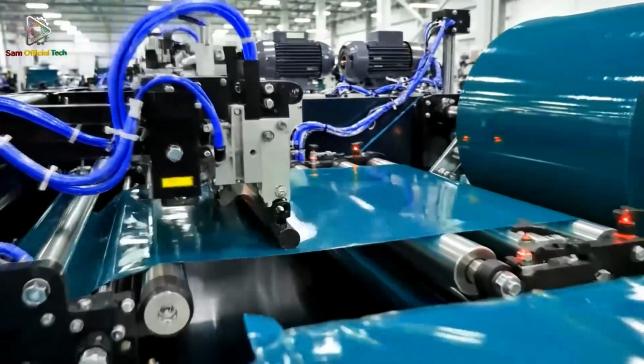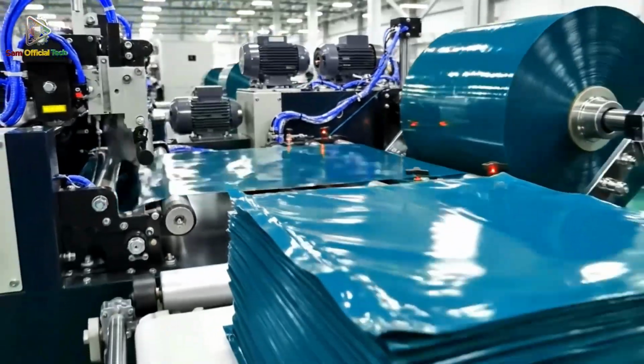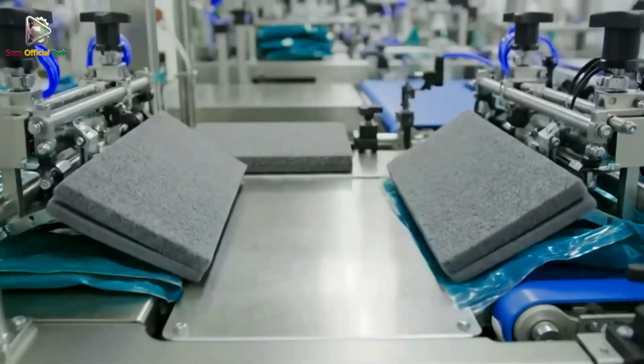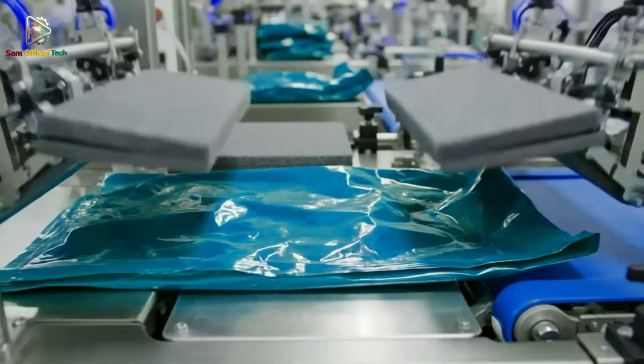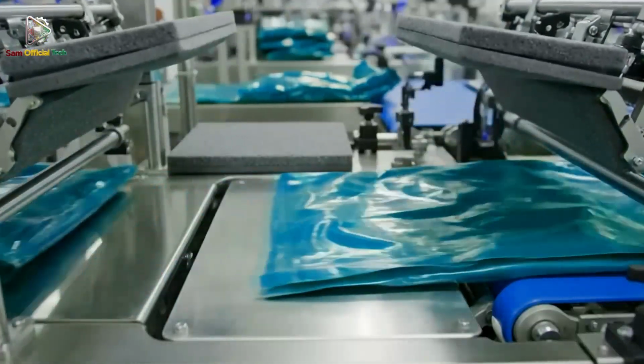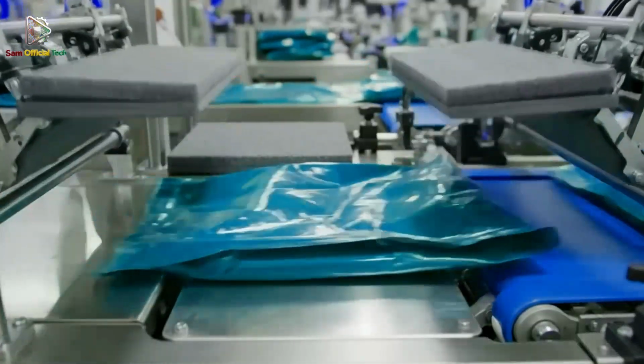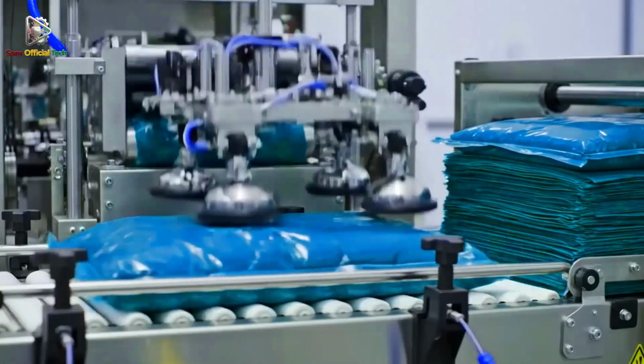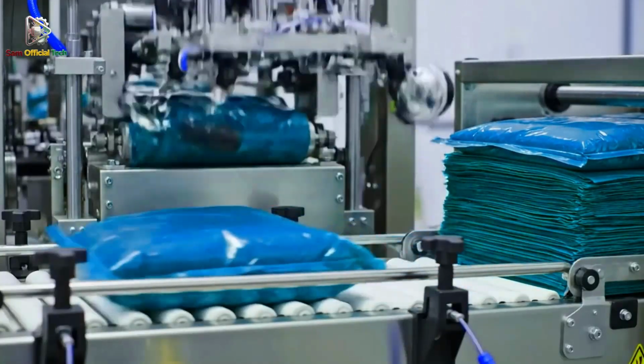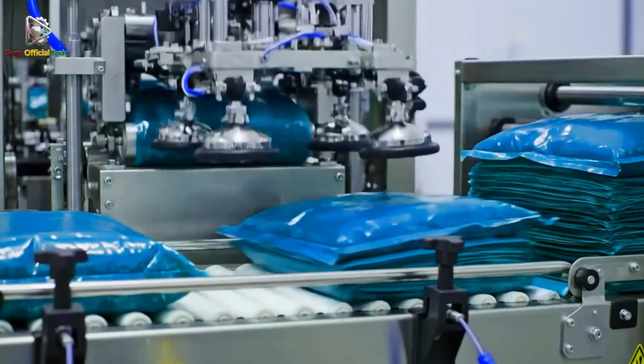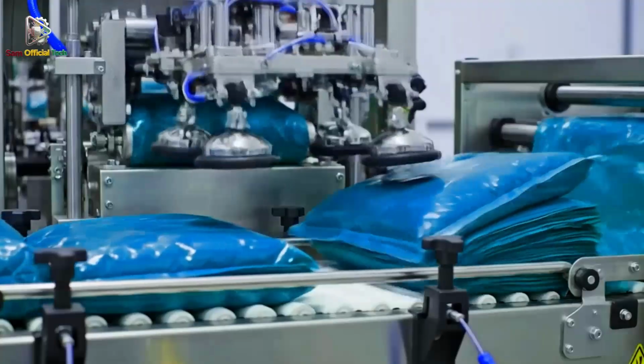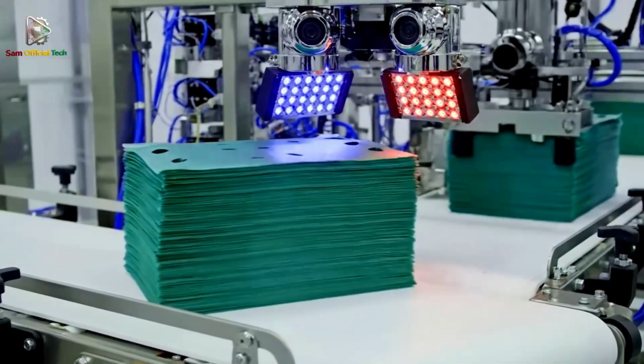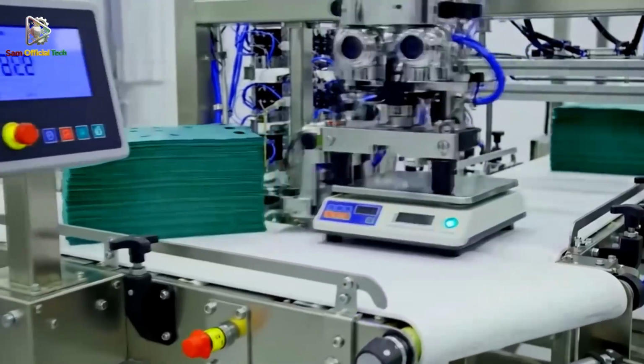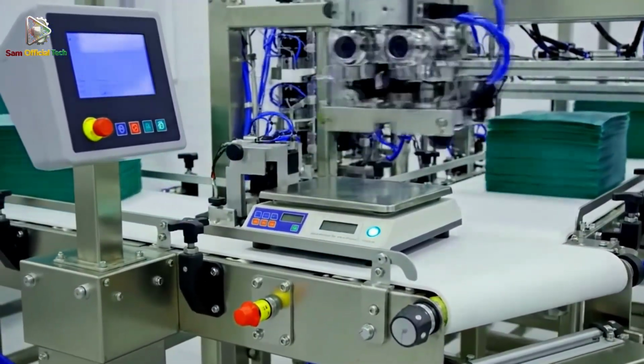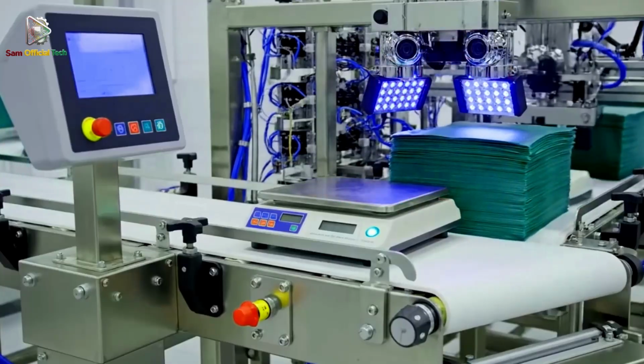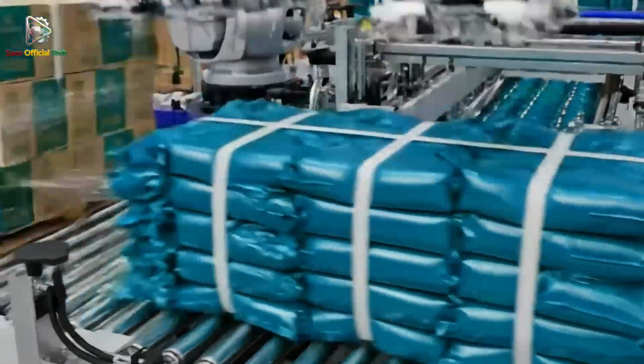Extraction is where the factory starts to look like a chemical plant. The seaweed slurry is mixed with an alkaline solution, often sodium carbonate, to solubilize the alginate as sodium alginate. Temperature, pH, and agitation are controlled tightly because extraction kinetics and polymer chain integrity are a trade-off. Higher temperature speeds yield, but can reduce viscosity by shortening chains. Inline pH probes and viscosity meters keep the process inside a narrow band so the output polymer can be formed into strong, flexible film.